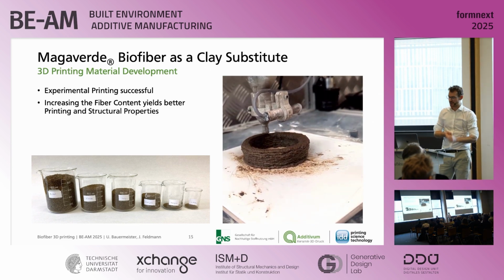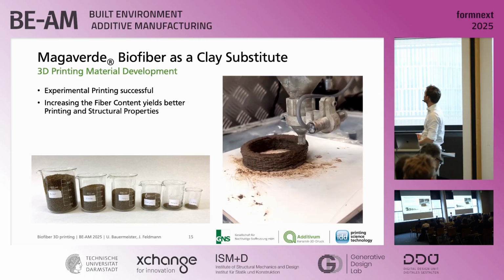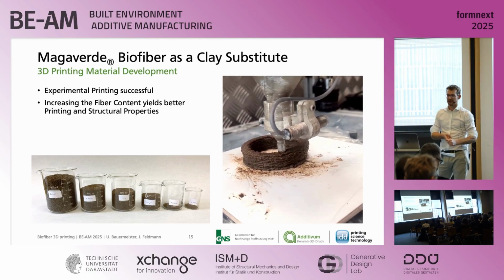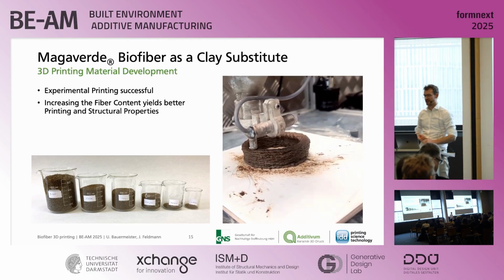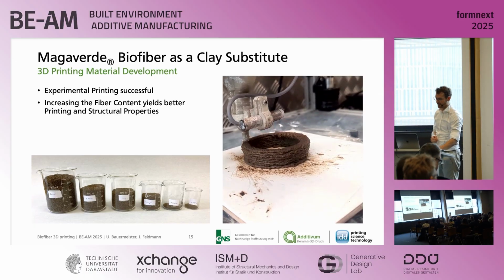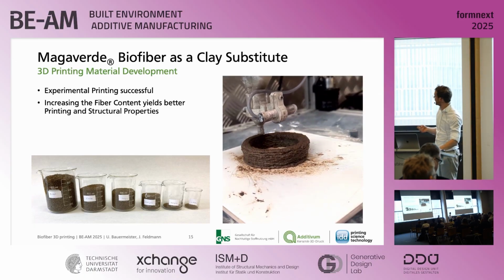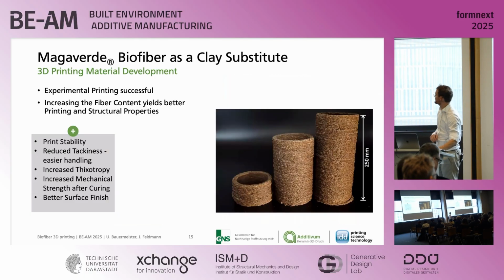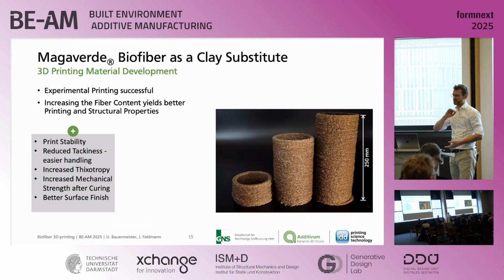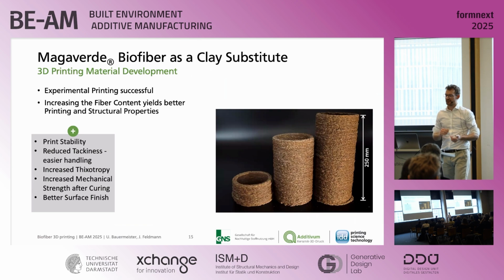So it was a huge mess, but we managed to get it under control by adding more fiber volume, especially shorter fractions of fibers. This increased the viscosity of it and also made it less tacky. But we also have other advantages by this. The whole print gets more and more stable by adding more fibers. So we encountered the problem, as shown in the video before, that the parts of the still soft material collapse under their own weight, and this got much better by adding more fibers, especially shorter ones.